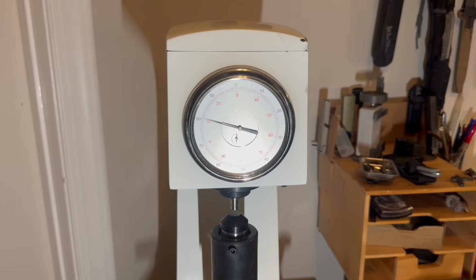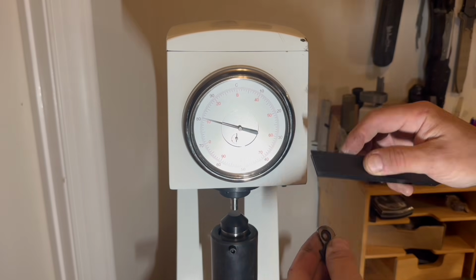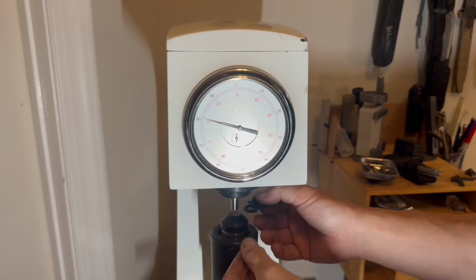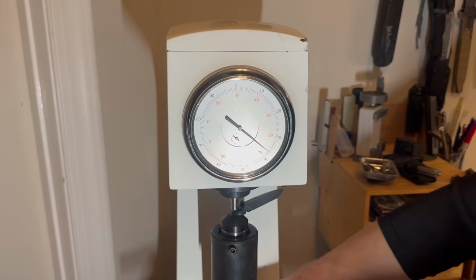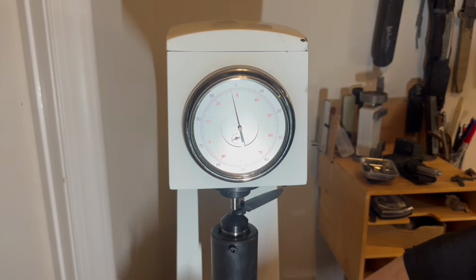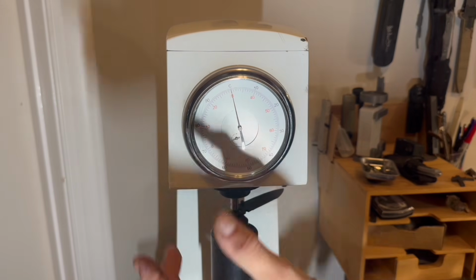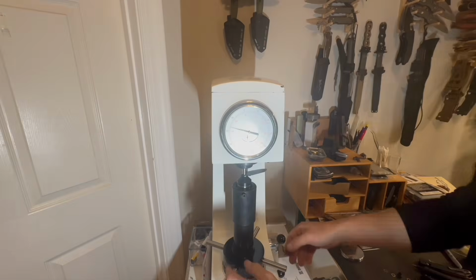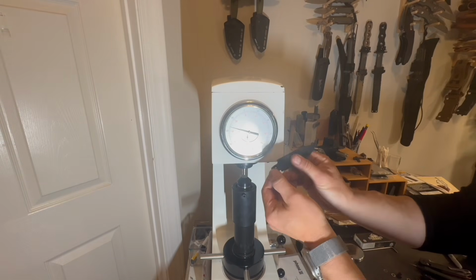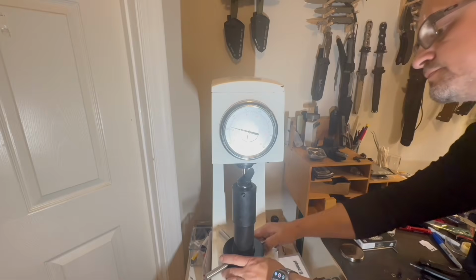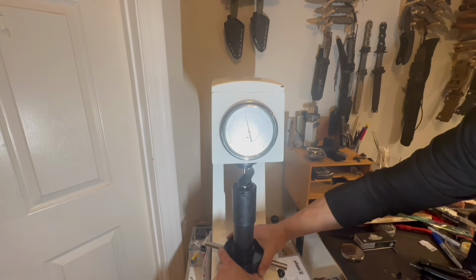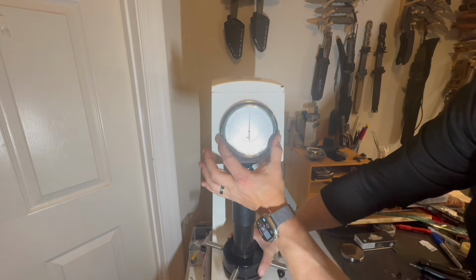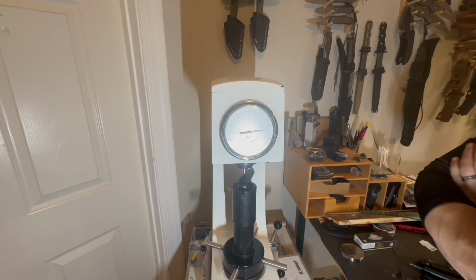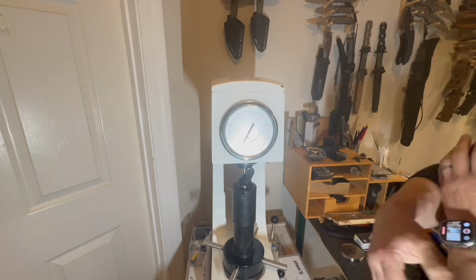However, the application of the coating itself is a heat-intensive process. I am removing the dimples here from the first two pokes to flip it over to the coated side. So when manufacturers do not pre-plan for heat-applied coatings, they are actually subjecting the blades to an additional tempering cycle. Whoops, my camera zoomed out. My wristwatch is my monitor, so it commanded it to zoom out. It's okay, we'll continue. I'm trying to keep the segment uninterrupted. So in my book, coating stainless blades to beautify them is doubly stupid. Tell you why in a sec.